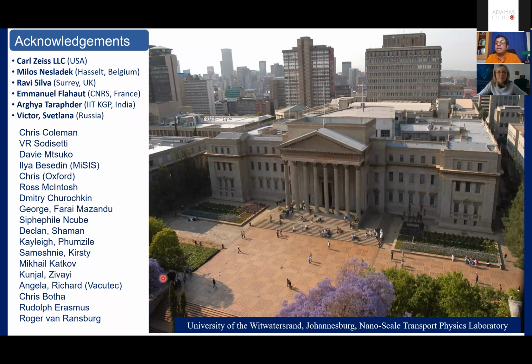Yeah, I just want to tell you this boron doping is done in the group of Professor Milos Nesladek in Belgium, Hasselt University, and he was very kind to offer me these samples, donated basically. It was done by microwave CVD, grown on quartz substrate, and the doping level is varied. Actually, boron percentage was varied over a few percent, but the level of doping was 10 to the 21, something like that. It's all written in our publications.